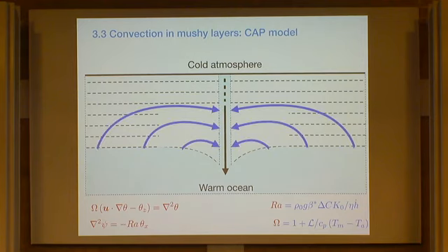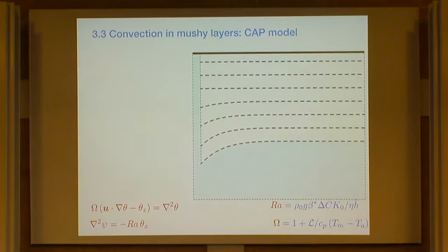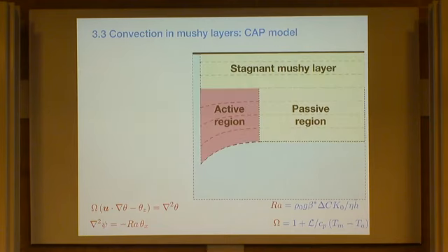And that drives a baroclinic or vortical flow as indicated by these blue lines, bringing in material which replaces the material which is going down the channel. So you can see that effect in this vorticity equation. The vorticity is driven by horizontal gradients. And so the model we're going to develop, to zoom in a little bit, we're just going to look at half of the domain by symmetry, and we're going to divide up our mushy layer into 3 regions.